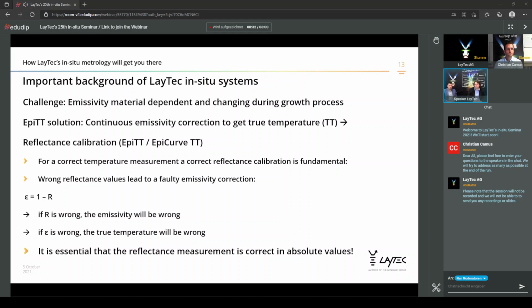So that means you are growing different layers, and it will change during the growth process. So the EpiTT solution, and this is valid for the EpiCurve as well, is a continuous emissivity correction to get the true temperature. To get there, you need, at the same time, at the same wavelengths, a reflectance measurement, and the reflectance has to be calibrated as well.